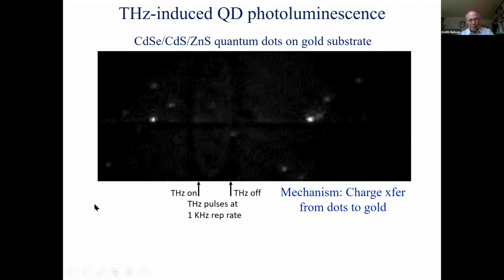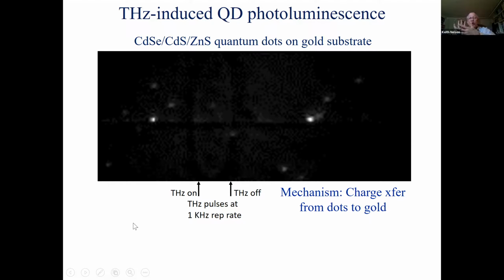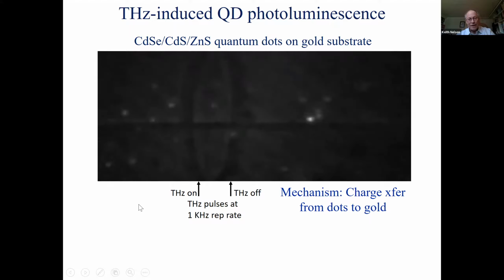Here's one more example. You should be seeing lots of light, photoluminescence from quantum dots in this sample. They are being irradiated by UV light. Visible light should be coming out. But it isn't, because they're on a gold substrate. And on that substrate, what happens is electrons jump from the quantum dots onto the gold, and the charged quantum dots don't emit light. The extra charge suppresses their luminescence.